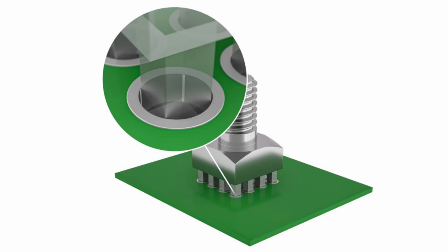Next, during the entire press-fit process, it's essential to support the press-fit zone. Without proper support, there's a risk of circuit board deflection during pressing. And this is especially crucial for pneumatic presses, where it's important to ensure that the stroke cycle is performed evenly and consistently. 3D printed or aluminum supporters are only suitable for a few samples. The stroke cycle should be executed in one movement, perpendicular and without angular misalignment to the PCB. This prevents defects in the via or even delamination of the printed circuit board.